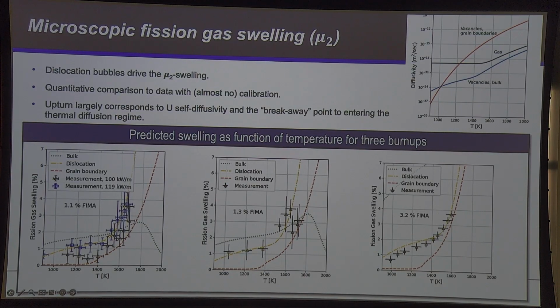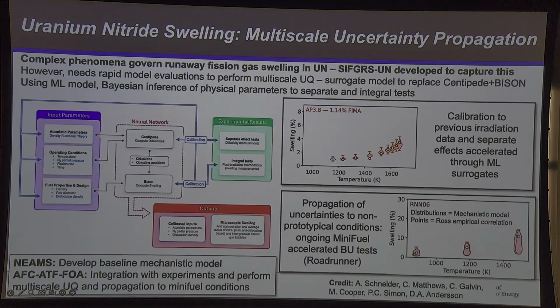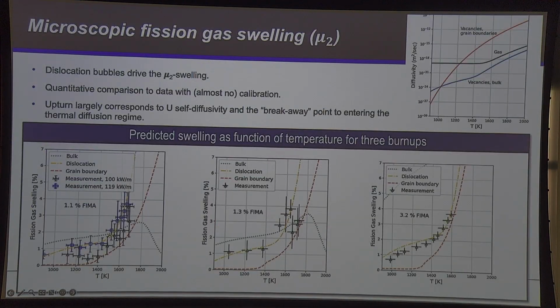And let's see, I think I have. The kink you see here is simply connected to the transition from irradiation-driven diffusion to thermal diffusion. So not a very complicated explanation, but it hadn't been identified, and that is what controls it. So as long as you avoid the high temperature regime where diffusion just gets faster due to thermally created defects, this fuel doesn't swell too much.